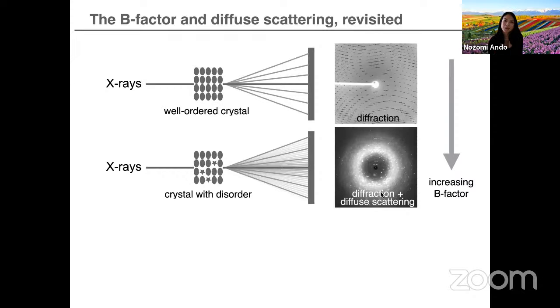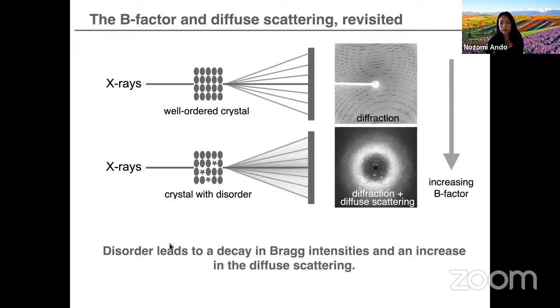And I already told you that the total scattering of a crystal is the sum of these two. So it's not surprising that if we lose any X-rays due to disorder and it doesn't go into the diffraction pattern, then it'll go into the diffuse scattering pattern. But there's more than that, which is that this whole process has to be related to the B factors as well, because any decay in the diffraction pattern that causes the X-rays to go in the diffuse scattering pattern is also modeled by the B factors. So just to reiterate, disorder in a crystal will lead to decay in the diffraction pattern, usually starting at the highest resolution. So this is why we lose the atomic details when we have disordered crystals. But that X-ray doesn't disappear, it goes into the diffuse scattering pattern. So it's still telling us something.